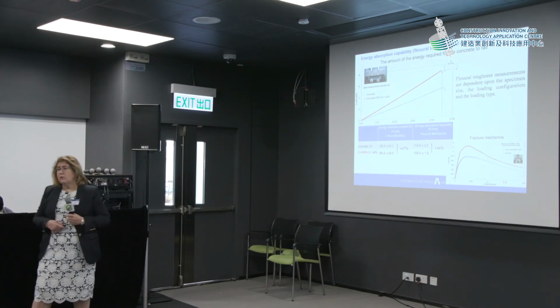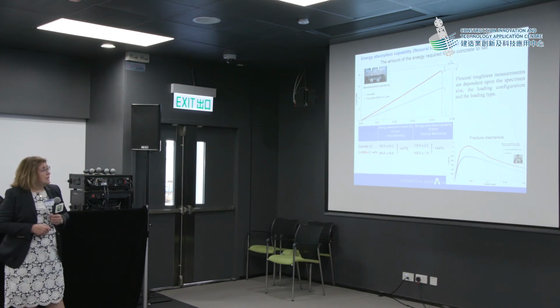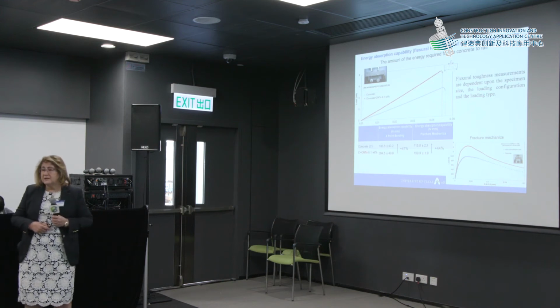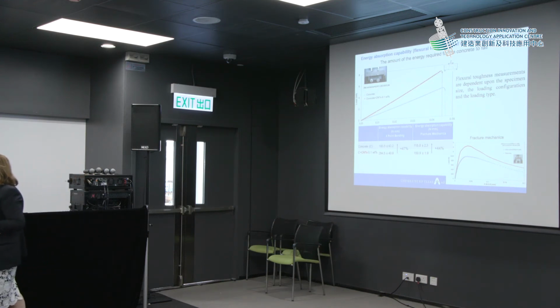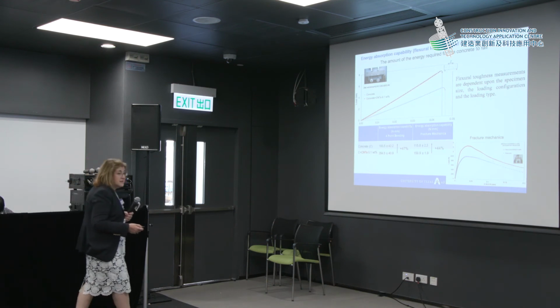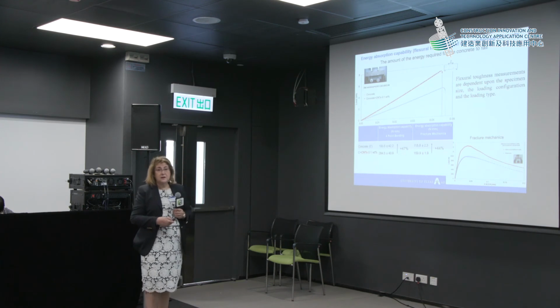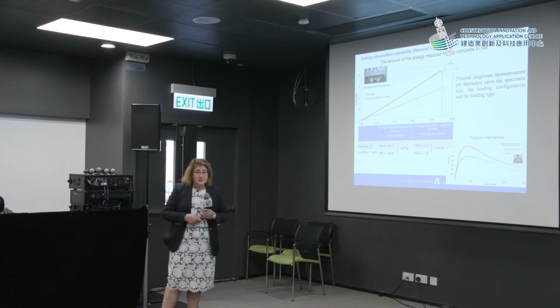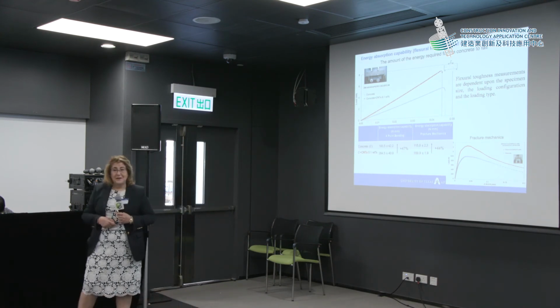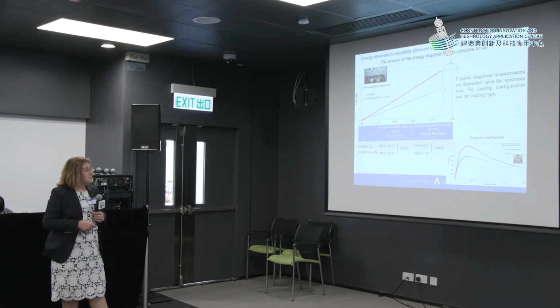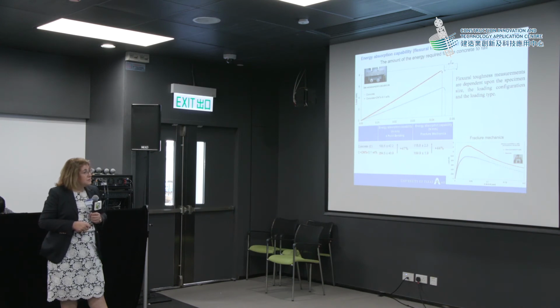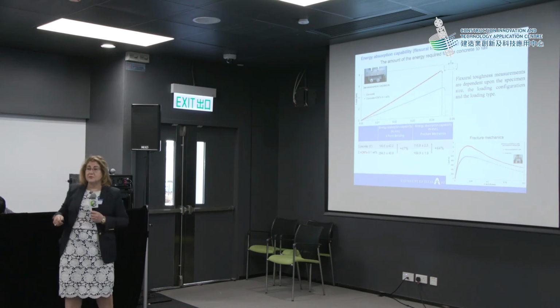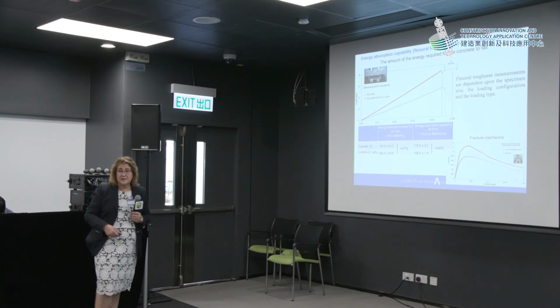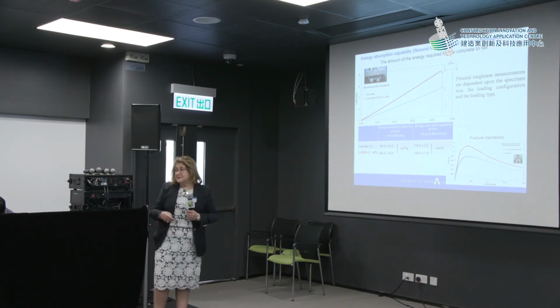The only thing that I want to show you right here is that 4-point bending tests have a disadvantage of giving us results that are size dependent. Fracture mechanics tests are giving us results that are size independent. And Professor Lang will remember with me Professor Bazant's theory about the size dependence of the problem that we face with size dependent specimens. But if you look at this, we have completely different values of the energy absorption capability, only that the percentage of the increase is the same. The values are different because we have size dependence, but the increase, regardless, is the same.